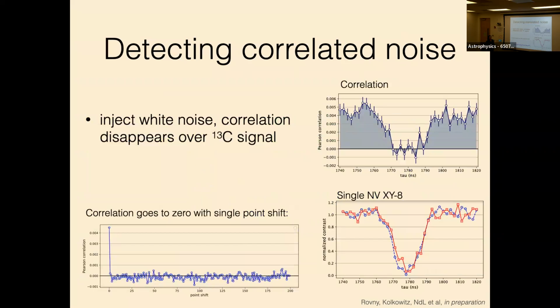Okay, and then now we can do this experiment that we did in numerics, where we just intentionally inject white noise into an antenna and then try and measure these correlations. And we indeed see very high correlations. And then we see that they disappear over the carbon-13 signal, and that it matches really well to just doing kind of traditional NMR of the carbon-13, where this signal appears. And importantly, when we do the single point shift where we expect the correlations to disappear, they really, really disappear. So we're sure that we're measuring a genuine thing.